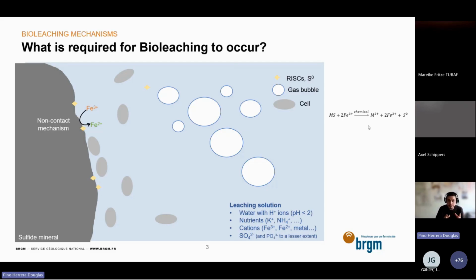And then we will have the production of reduced sulfur compounds, which is represented here by the elemental sulfur. So actually, what bacteria are going to do is to regenerate the ferric ion to continue the reaction, and also to oxidize the sulfur compounds into sulfates. And to do this, they are going to need oxygen. They're going to consume protons, so acidity from the system, but they're also going to produce acidity from the sulfur compounds.